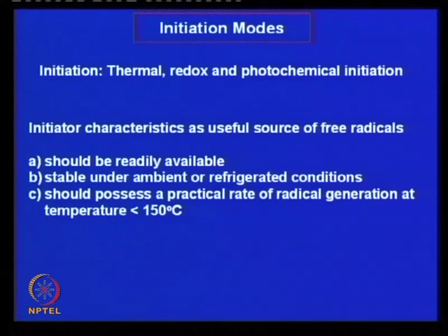Now, if there is a possibility of breaking a monomer molecule, thermal homolysis of the olefinic monomer double bond, that free radical will be scavenged or stopped by interacting with the hydroquinone radical. So, even if there is initiation, the inhibitor will inhibit its growth. That is called inhibition. Okay. So, thermal initiation is possible, photochemical initiation is possible.